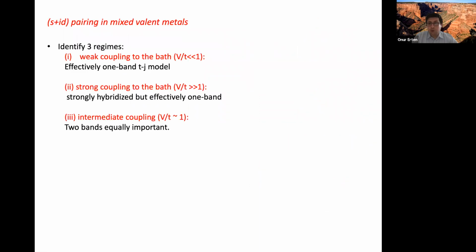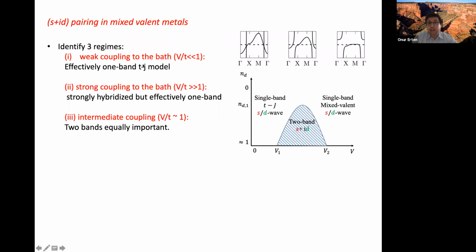Right, so before I go to the results, we identified mainly three different regimes. The first regime is the weak coupling to the bath. If the coupling to the bath is very weak, practically nothing happens. We still have a one-band t-J model. Then we have a very strong coupling to the bath. In this case, we have very strongly hybridized bands, but effectively you still have a single Fermi surface. And at intermediate coupling, when the coupling to the bath is order 1, then we fall into a two-band picture where both bands become equally important.